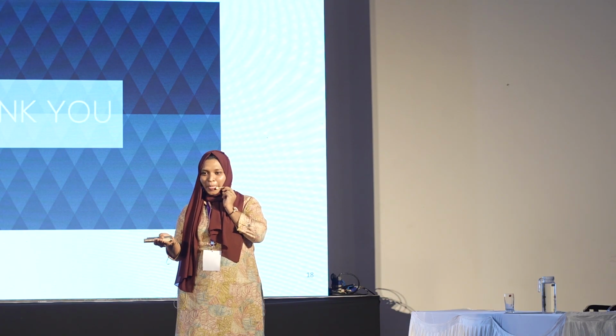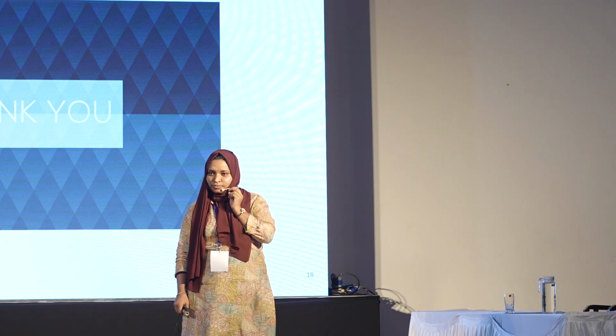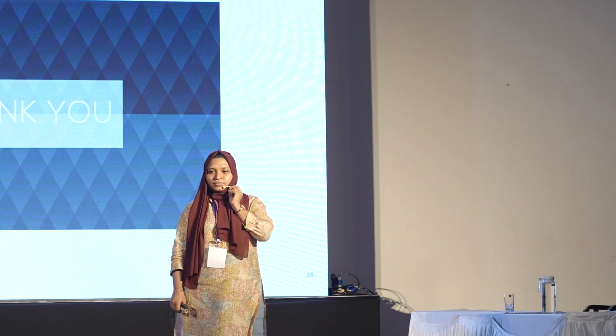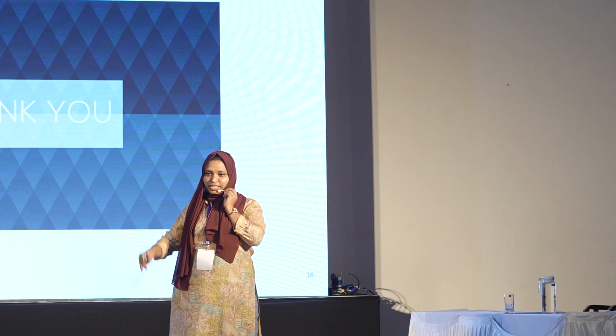Nice presentation. How did you find out the potential window for your three systems? How did you find out that is the correct potential window? For cyclic voltammetry, we would be doing scans over a wide range, and then wherever we get the peaks, we would be shortening that range to enhance the nature of the peak. Also, we would refer to the literature as well. Yes. Are you sure that there is no irreversibility involved in this potential range? Mostly for ascorbic acid, it is not reported. It is the resolved oxidation peak that is mostly seen.